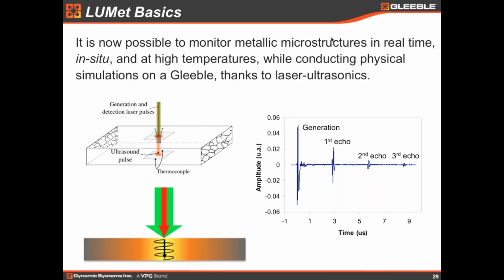The speed of sound can also give us texture information, because it is going to be different in the different crystallographic directions of a sample. So for instance, if we had a single crystal sample, I would get a very different speed of sound depending on which direction through that crystal I measured the echo and the return. That can give us information on annealing, because if, for instance, I have a sheet and I'm annealing that sheet, I can look at the texture change from the cold rolled texture to the fully annealed texture, and I can get information on that.